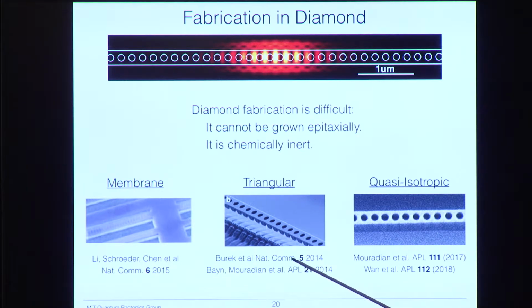The second is this triangular etch. So what you do is you start with a bulk diamond, and you etch at a slant from both sides, and so you create a structure that is fully suspended but has a triangular shape, so you get these kind of Toblerone-looking structures. So Harvard has pioneered this, and we have also shown decent cavities with this. Unfortunately, you get a kind of strange mode structure that is difficult to couple into other photonic structures. And also you can get more surface roughness because it's a pretty rough etch.